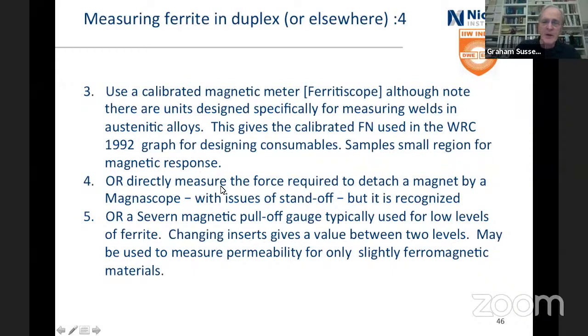There's the Magnascope. Basically, you hold a magnet against it and pull it off and look at the force, and that gives you a number, but it is recognized. Or the magnetic pull-off gauge, which is really dinky. You put a little tab in it and see if it lifts off, and if it does, then you go for the smaller one and just keep going between them. And you get a number that is between 2 ferrite levels, used for small levels of ferromagnetism.